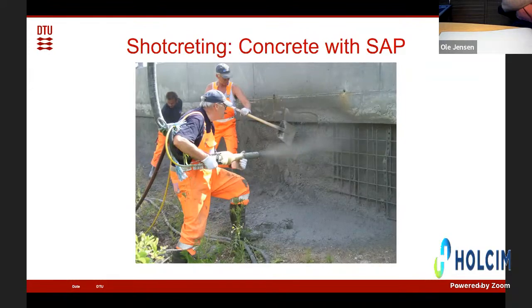During shotcreting with the wet method, you need a very fluid concrete to allow it to be pumped. But as soon as the concrete has been projected to the wall, you like it to stiffen, to be able to build up thick layers. And this can be done by adding dry SAP in the spray nozzle.